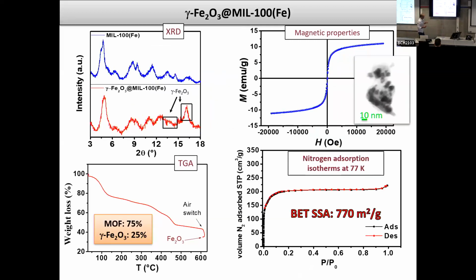As a last part of this project, we characterized the composite material coming from the fusion of the two systems. In the X-ray diffraction analysis we found the peaks of both crystal structures, and in the thermogravimetric analysis we observed an increased percentage of metallic parts due to the presence of the iron oxide magnetic nanoparticles.